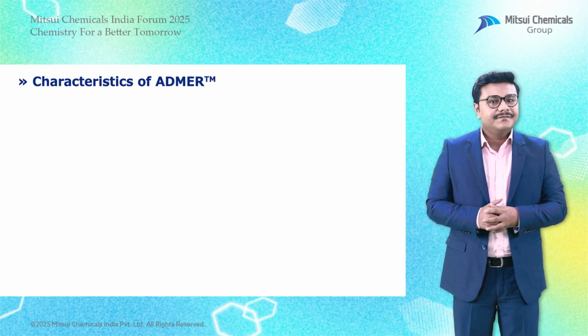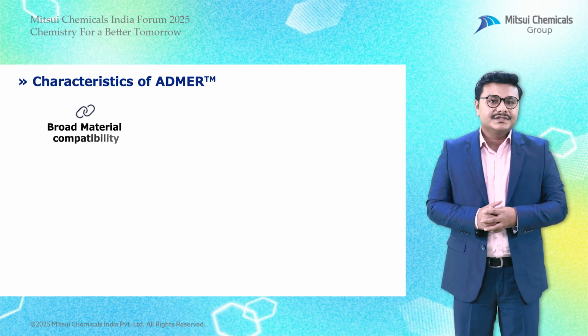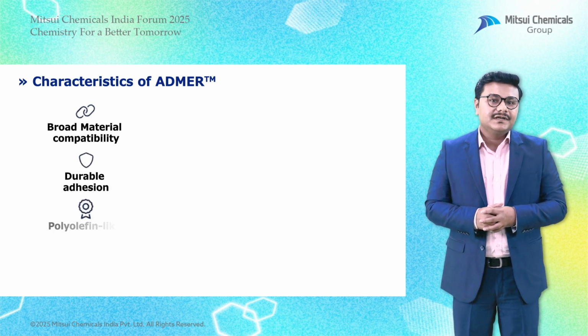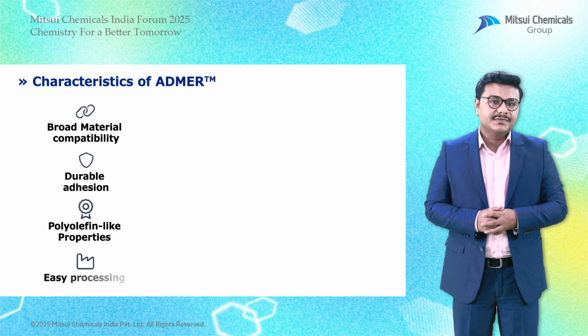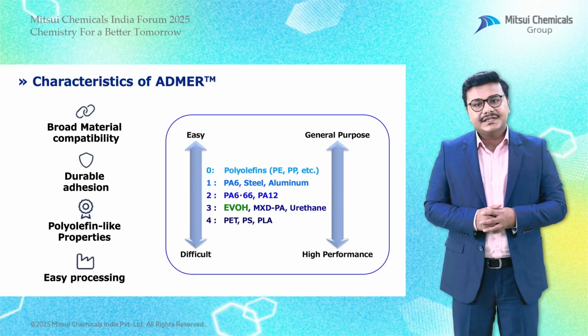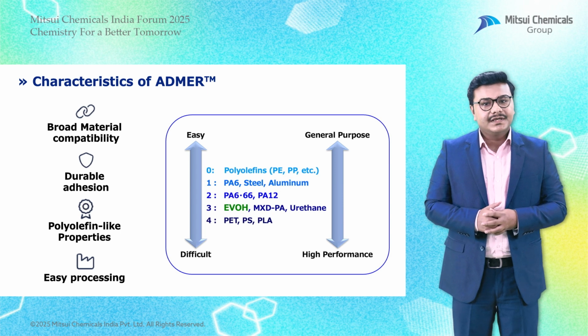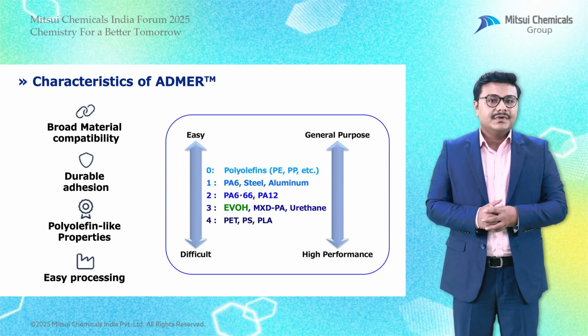Admer shows different characteristics, which include its broad material compatibility, durable adhesion, polyolefin-like properties, and easy processing method. It gives adhesion to different substrates ranging from polyethylene, polypropylene to nylon, aluminum, and to barrier materials like EVOH and MXD nylon, urethane as well, and many polar substrates as well.